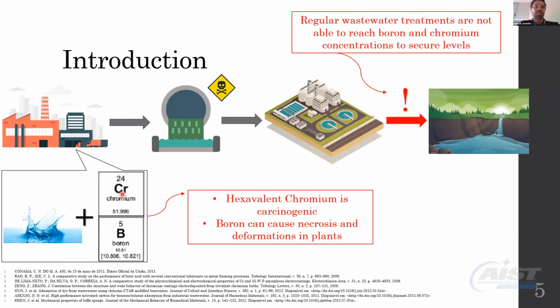Siderurgical industries use boric acid as a lubricant in mechanical conformation processes and chrome in electrochemical baths to increase mechanical resistance and avoid corrosion in the steel. Even after regular wastewater treatment, the substances can be found in trace concentrations in the treated water. Removing these trace concentrations is really hard and new technologies are necessary. Chrome is well known to be carcinogenic when ingested, and it's bioaccumulative. In other words, after ingestion, it accumulates in the body tissues. Boron, for example, if it's in high concentrations in the soil, can cause deformations in plants and necrosis, and even can devastate an entire plantation.